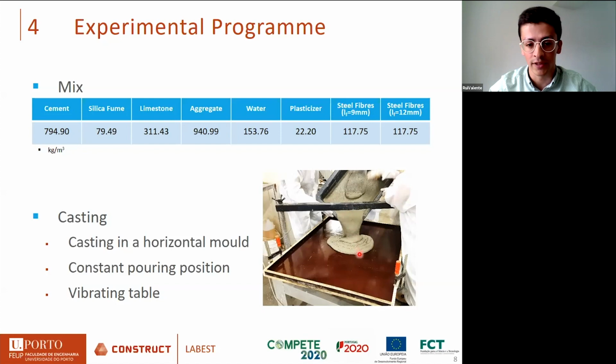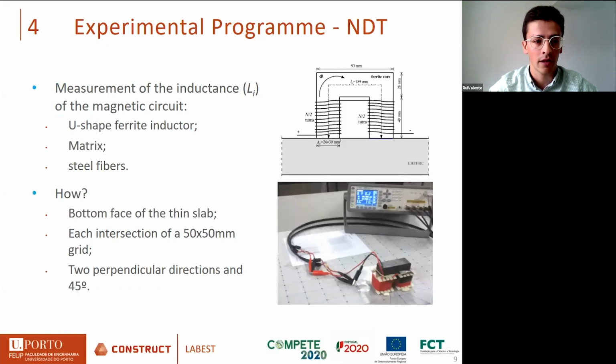So viscous that unfortunately it resulted in some roughness of the top surface of the casting and consequently in some variation of the plate thickness. I will come back to that later. When the plate solidified, we performed non-destructive tests by means of the measurement of the inductance of the magnetic circuit comprising this U-shaped ferrite inductor, the matrix and the steel fibers embedded in there.